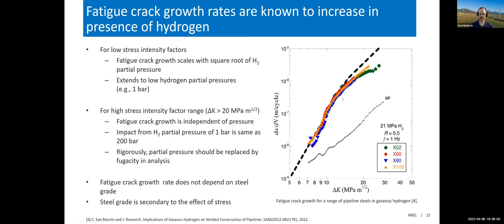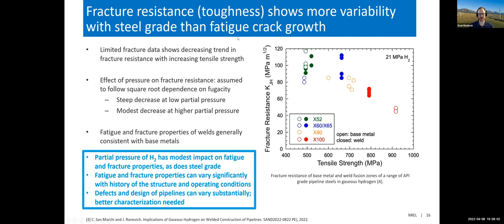Another thing that we can take away from this is that fatigue crack growth rate does not depend on steel grade. So the steel grade is really secondary to the overall stress intensity. If we look at fracture resistance or fracture toughness, here we see a little bit more variability with steel grade. There's a general trend with somewhat limited data that shows that as you increase tensile strength of a metal, the fracture resistance decreases. So I think this is fairly well understood that